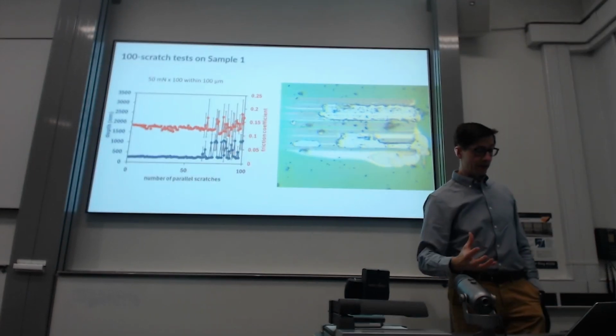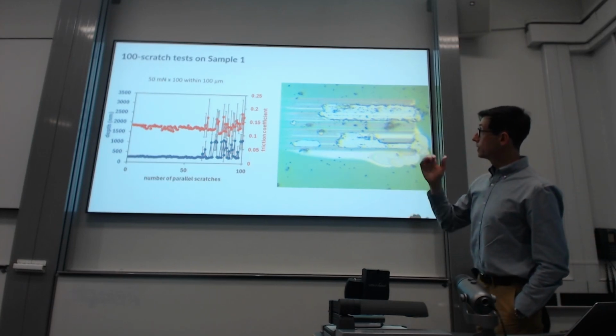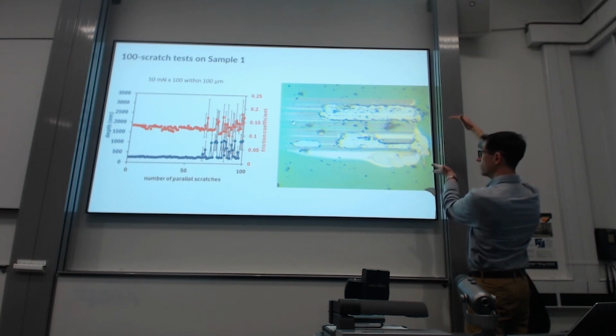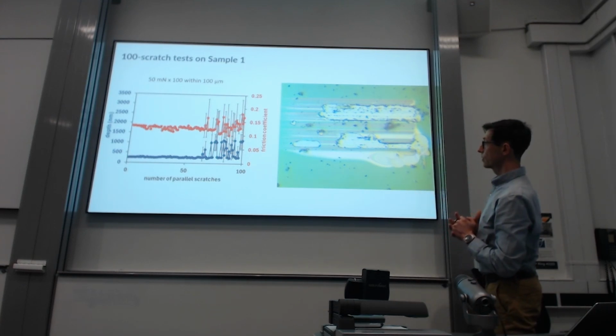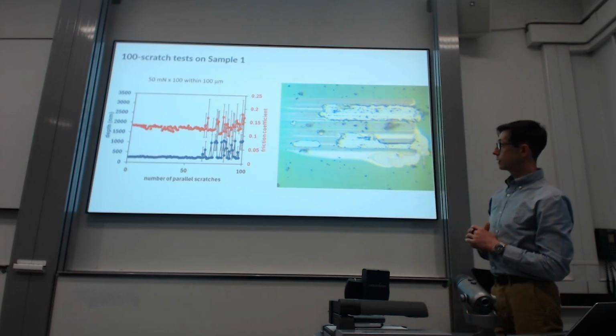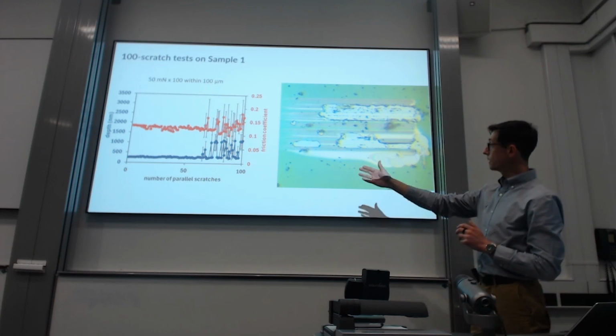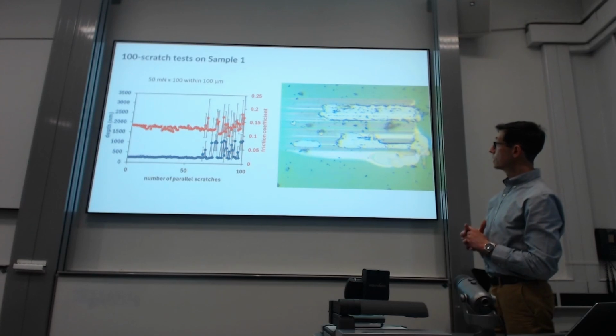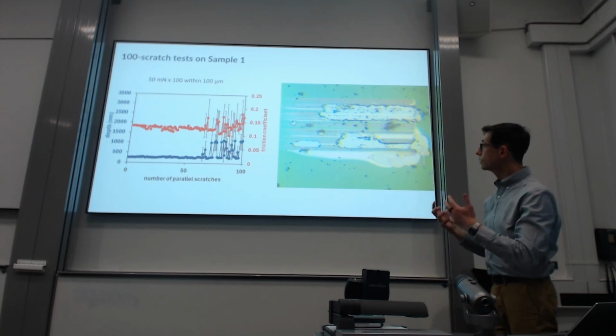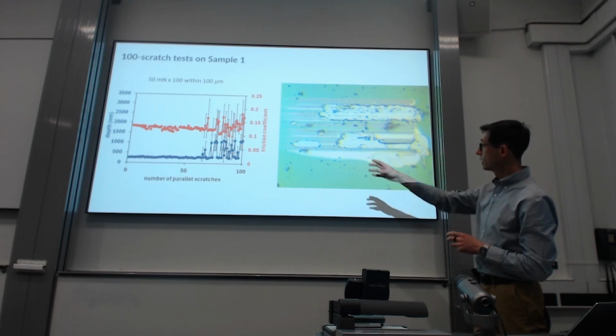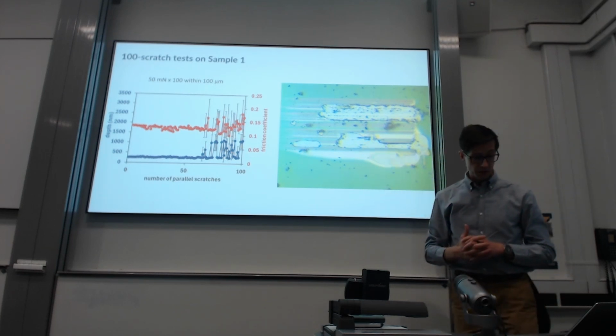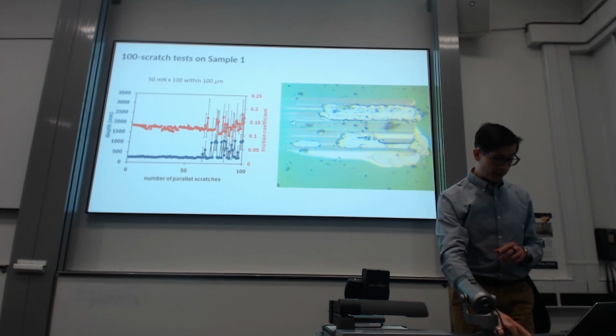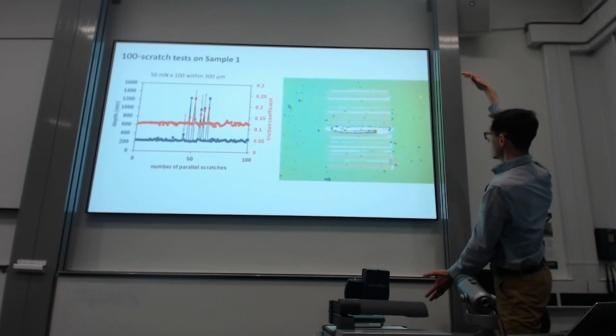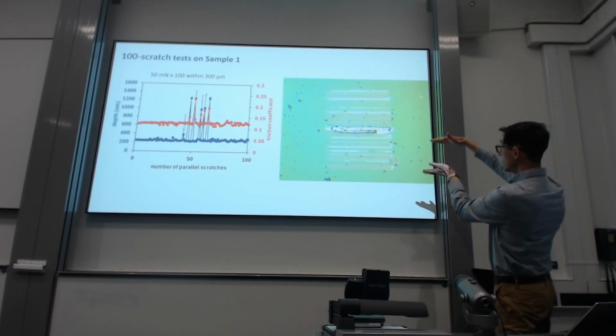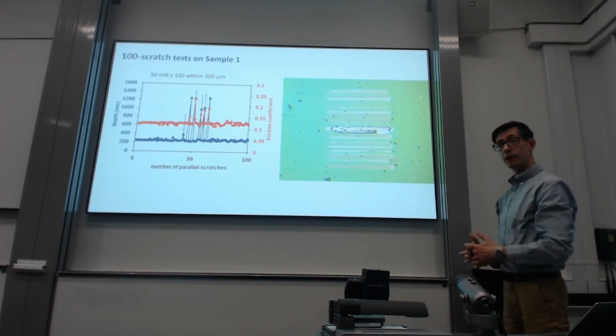We decided to run 100 scratch tests on that particular sample, and we started with 50 millinewtons load and a 100 wide area for those 100 scratches. Again, you can analyze your results in terms of depth and friction coefficient as a function of number of parallel scratches. For those loading conditions, you can see around 60, 65, you start inducing quite significant damage. You start observing some blistering, which is clearly recorded as an increase of depth and increase of friction. In the second case, we decided to keep the same load, but increase the area we cover with the scratches. So we moved from 100 to 300 width, if you like, of that testing area.